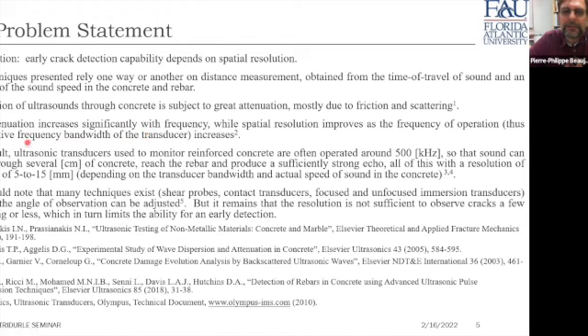If you want to actually get a better spatial resolution, the sound cannot actually get in as far in the concrete. The result: ultrasonic transducers used to monitor reinforced concrete are often operated around 500 kilohertz, which is going to be the sweet spot in frequency where you get the best compromise between pretty much the range of operation, how deep the sound can go in the concrete, and how good a frequency and spatial resolution we can get.